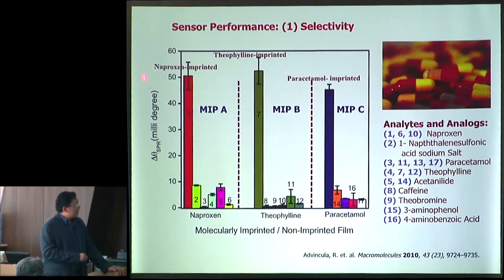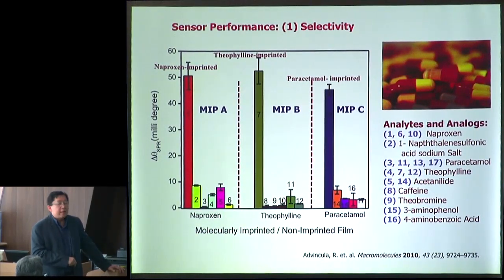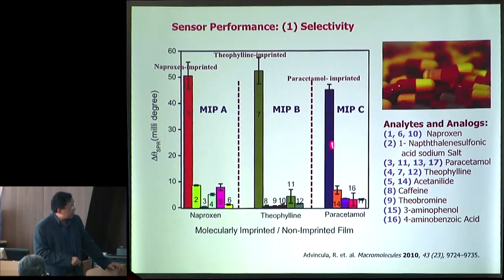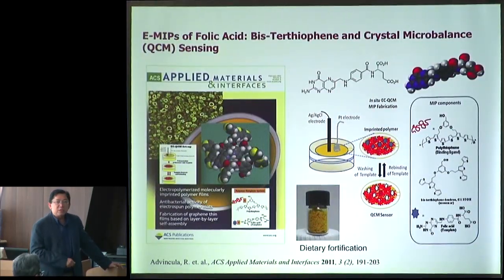So the result is as follows. When we templated naproxen, the rest of the molecules did not respond. When we templated theophylline, the rest of the molecules did not respond. Notice that caffeine and theobromine have almost similar structure as theophylline. Shows you how sensitive the film is to the original template. Or paracetamol, the same thing. So this is what we call highly sensitive or selective films, even with a dynamic range that we have found to reach to picomolar level.